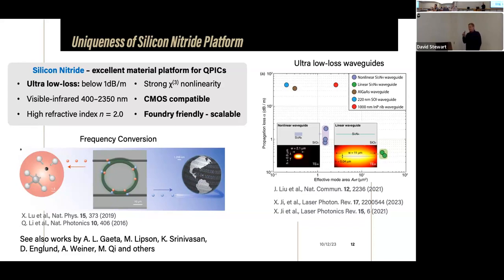Refractive index is relatively high, which is of course important for confinement within a waveguide. As I pointed out already, this is indeed foundry friendly, scalable, it's the most compatible, and the transparency window is quite huge, between blue light and down to 2.5 micron. And here you could see some typical propagation losses for different types of materials, and you could see that in this case, silicon nitride goes down to 0.1, sorry, or maybe 0.2 dB per meter, but it's quite close. And as I said, it's still far from what you, in principle, should be able to accomplish. People are still working to decrease losses in this material.